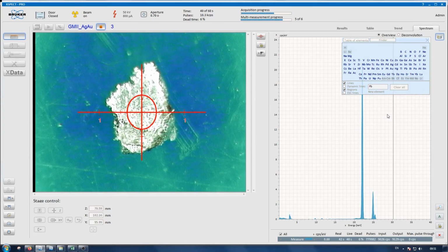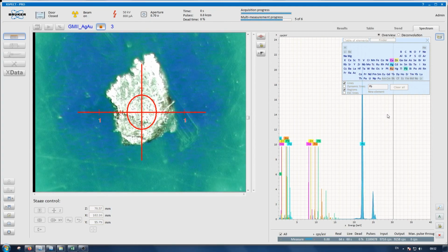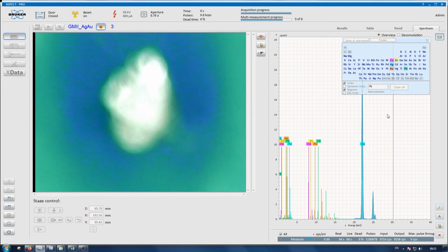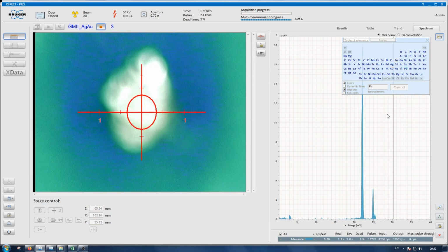The micro X-ray fluorescence analysis showed that the silver rhyton from the Novokumak burial mound was made of a silver alloy, ligature. The silver content in all samples exceeds 98%. The alloy composition also contains minor inclusions of gold, 1.5%, copper and lead, hundredths of a percent. Inclusions of these elements as impurities are necessary to improve the mechanical, physical, and chemical properties of the alloy. The material of this vessel is a high-grade silver, 990, which fully corresponds to the metal purity of other Achaemenid silver rhytons as well.